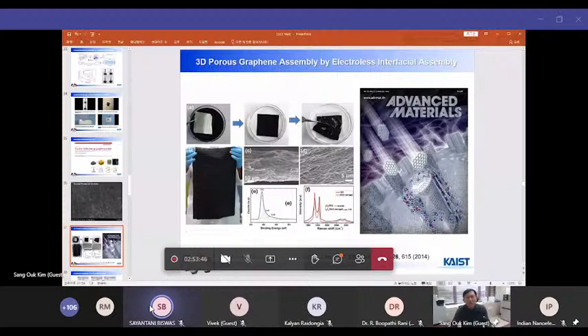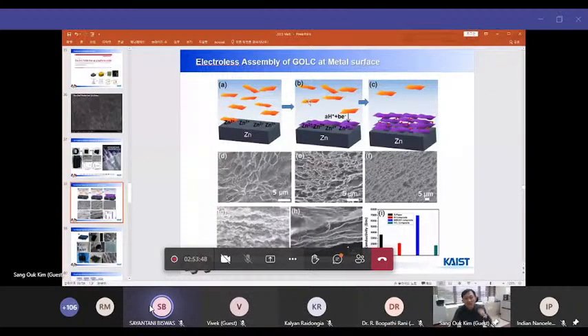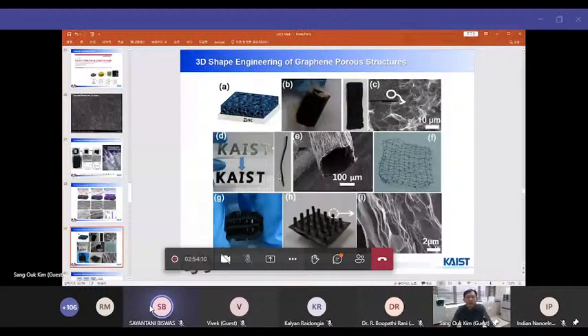Actually, the underlying principle is electroless deposition. When zinc is dissolved in graphene oxide aqueous dispersion, the graphene oxide is reduced due to the reduction potential difference with zinc. And he could also obtain layered composite structure by incorporating nanoparticles and nanowires. And he could also obtain this structure at the surface of textile, right? Flexible textile.